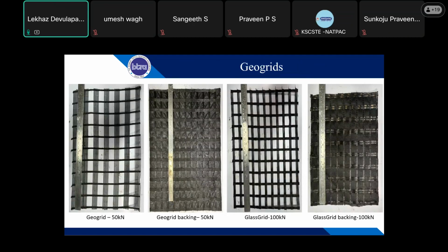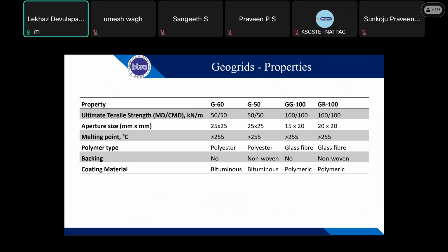Even the research has also started for the coating. Since we are using it in asphalt materials, we want a coating of the geogrid that should be compatible with the asphalt. So when we discussed with the industry, initially they used to have the PVC coating or the polymeric coating, but that doesn't have a proper bonding with the asphalt layer. Then we started with bituminous coated geogrids, especially for asphalt reinforcement. And for the glass fibers, they are still changing the polymeric coating into a bituminous coating.